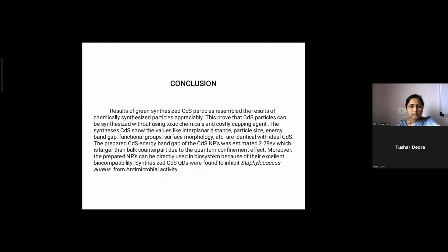Conclusion, ma'am. I concluded that the green synthesis of CdS particles resembles the results of chemically synthesized particles. This proves that CdS particles can be synthesized without using toxic chemicals and costly capping agents. The values like interplanar distance by XRD, particle size by XRD, energy band gap by UV, functional group by FTIR, and surface morphology by FESEM are identical with the CdS in bulk. The energy band gap of the prepared CdS nanoparticles was estimated at 2.78 electron volts, where the ideal was 2.4, which is larger than bulk due to the quantum confinement.